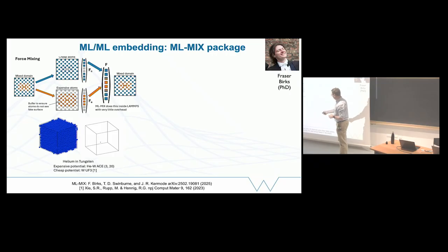So we have a big box of tungsten. Mostly the tungsten is just flopping around in a harmonic regime. It doesn't need a very accurate model to describe it, but the interactions between the helium and the tungsten can't be captured by a simple model. So here for the expensive potential, we used an ACE, similar to the ones I just showed you for the fracture case. And for the cheap potential, we used something called UF3 from Matthias Rupp and Richard Hennig, which is really a generalized two-plus-three-body potential.